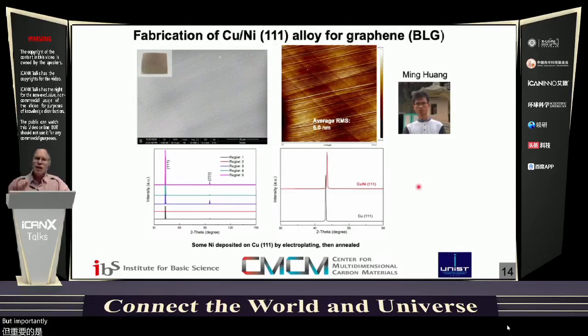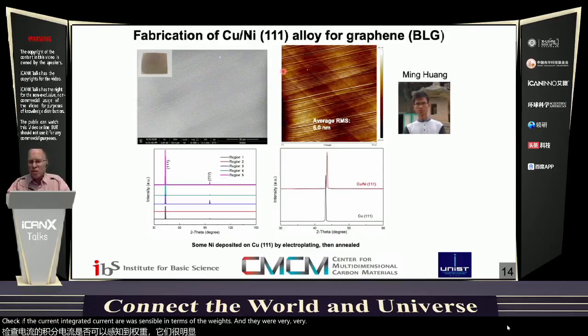But importantly, every time a nickel 2+ ion arrives at the copper and gets reduced and plates out nickel, two electrons go through the external circuit. So measurement of the current can allow actually knowing the nickel concentration to 3 and maybe 3.5 significant figures, which can be very valuable. Of course, we also weighed the copper foil beforehand. And then after, we would check if the integrated current was sensible in terms of the weights, and they were very, very close.